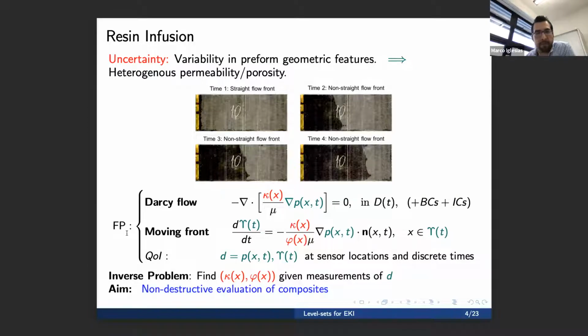This is FP, for forward problem. So we have a Darcy flow, which is this second order elliptic equation, where the variable here in red, kappa, is the permeability of the preform, mu is the viscosity of the resin, and P is the pressure of the resin at a given position in the preform at a given moment in time. And that's defined in a domain that is changing, it's variable. So this is a moving boundary problem, where you see in this picture the moving front, which in the equations is gamma T.